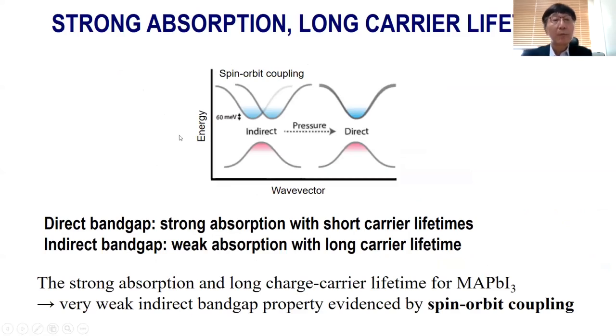And also, for instance, usually a direct band gap transition material has a very strong absorption, but a very short carrier lifetime because of the direct band gap transition, the energetics. However, the perovskite has very strong absorption along with long carrier lifetime. This is because of the spin-orbit coupling characteristics.